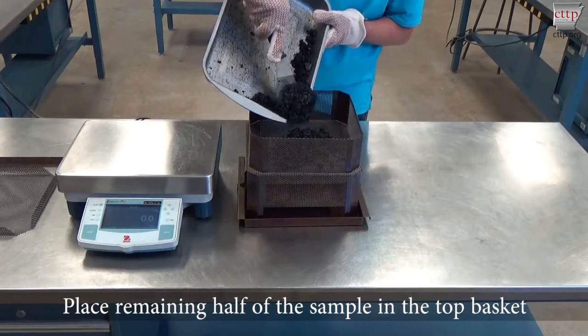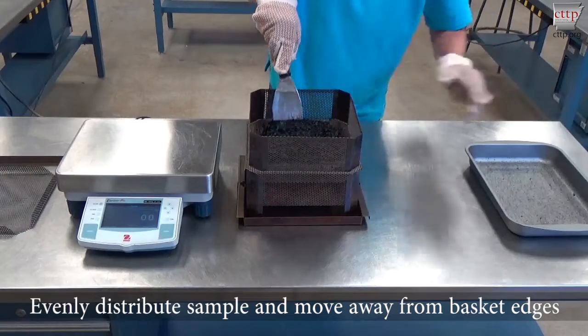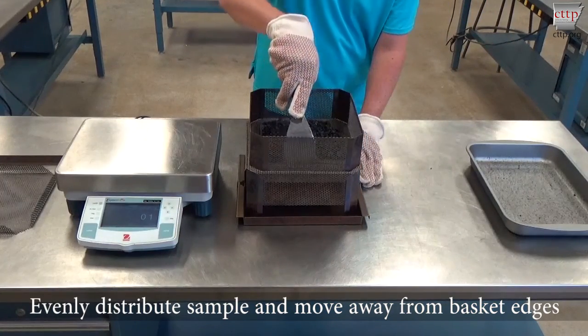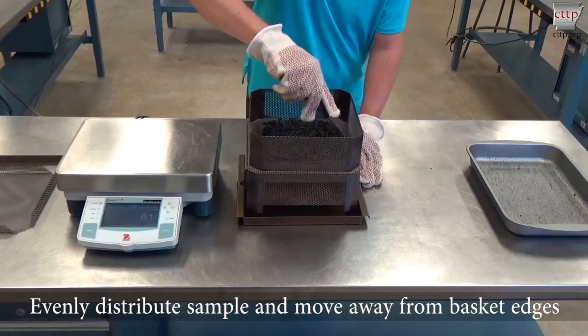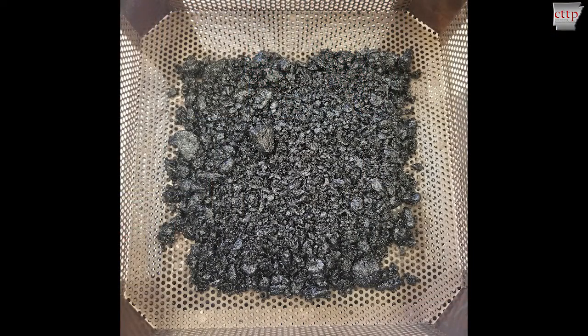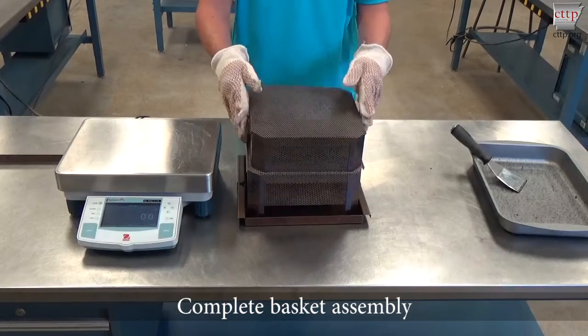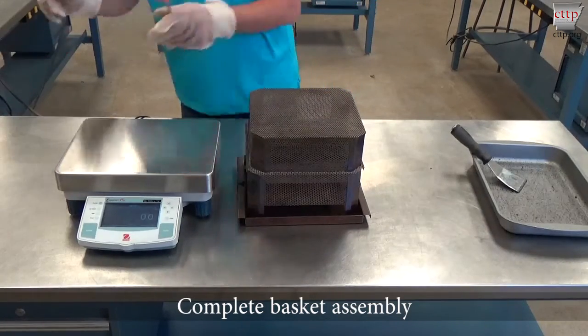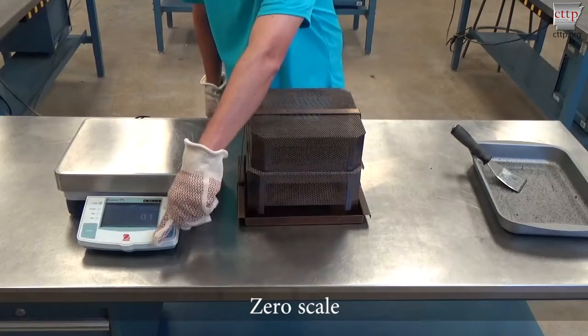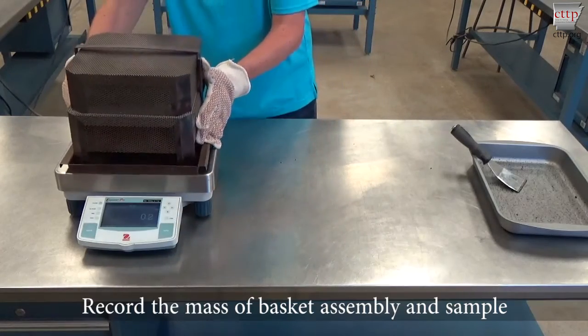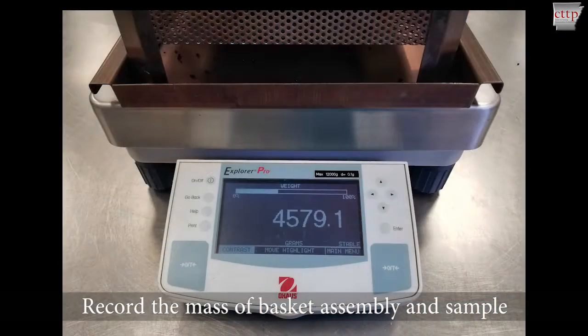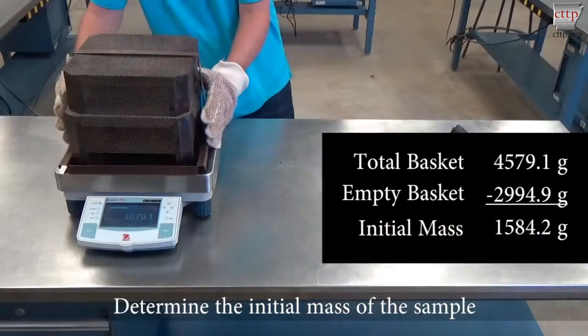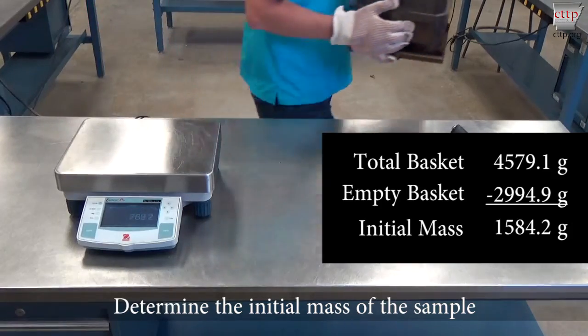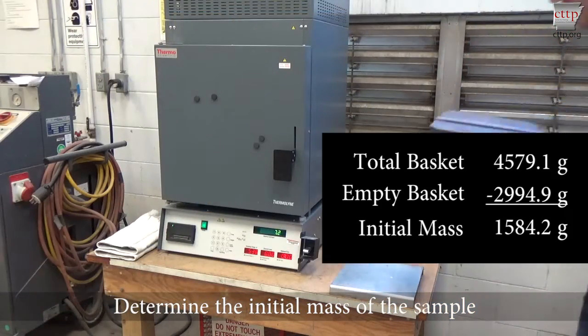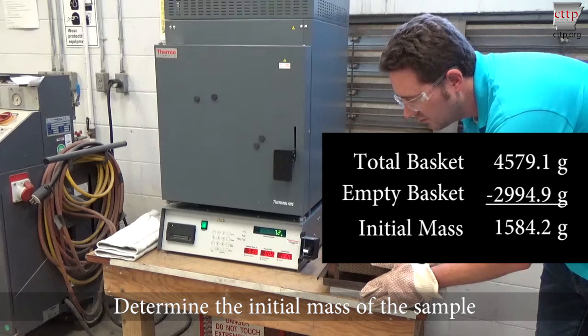Place the remaining half of the sample in the top basket. Evenly distribute the sample and move the mix away from the basket edges. Complete the basket assembly by securing the lid and assembly guard. Zero the scale and place the basket assembly on the scale platform. Record the total mass of the basket assembly and sample. Determine the initial mass of the sample by subtracting the mass of the empty basket assembly from the total mass of basket assembly and sample. Round the initial mass of the sample to the nearest 1 gram.